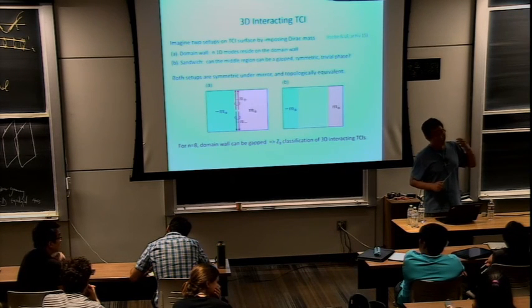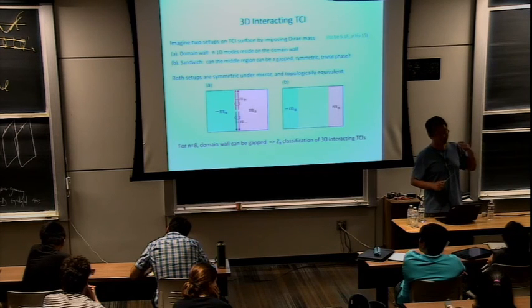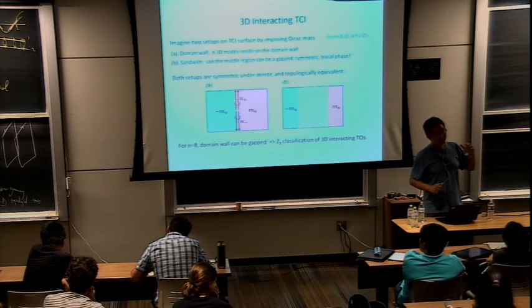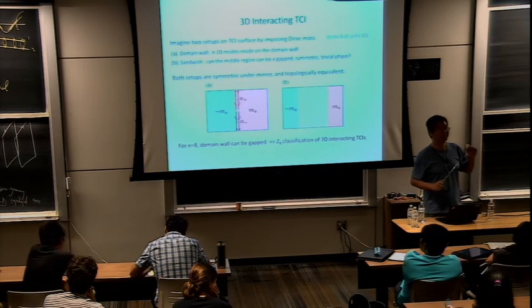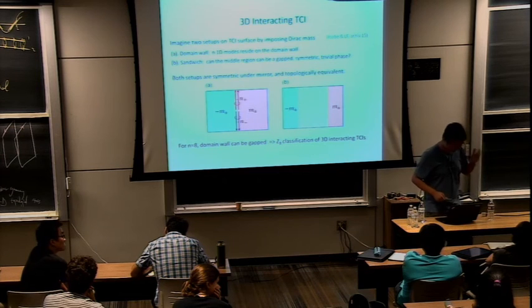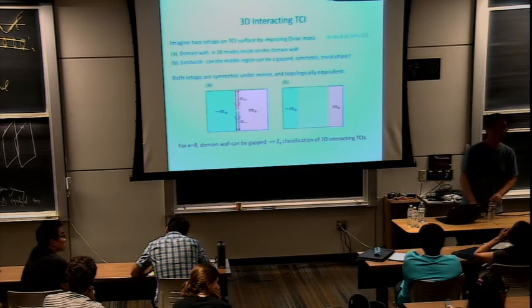So in order to infer whether the topological phase is stable against disorder, it's sufficient to just ask first whether surface disorder destroys the surface states. So the defining property is that the topological states have to be robust against arbitrarily strong disorder on the surface. So that's the criterion, at least for the fully robust topological states.